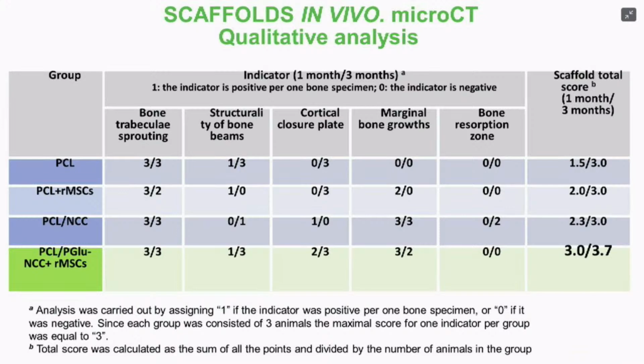In other groups, the difference that we observed for the bones removed within 1 month after surgery, while the overall score for scaffolds implanted during 3 months was the same. It must be noted that new bone mass generated by scaffolds was more pronounced both after 1 and 3 months in the case of this last group, marked green. So we could conclude that our biocomposite material, seeded with rabbit mesenchymal stem cells, actually improves the bone healing process, at least in rabbits.